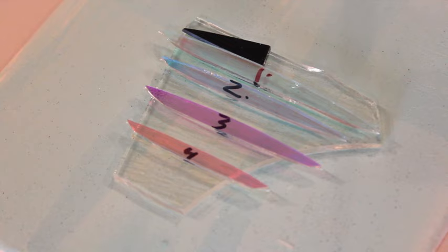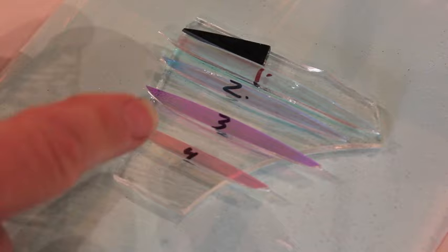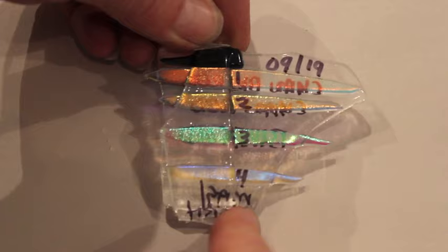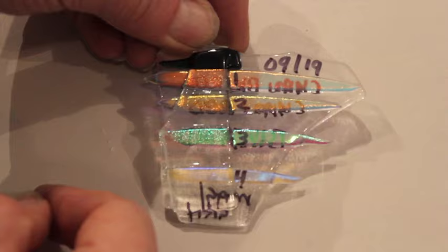Here I'm testing my clear pieces from this order, and I've got the coating side face up. I'm going to cover half of it with a piece of clear so I can get a test result from exposed coating and coating that's been cased under clear. I'll fuse this and write the date on it and keep it with my stock. Here's a look at my sample now that it's been fused — I can get a better idea of which coatings that are exposed are too scratchy to use in some of the embossing that I'm doing.